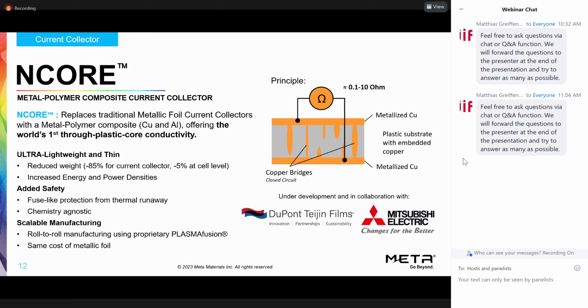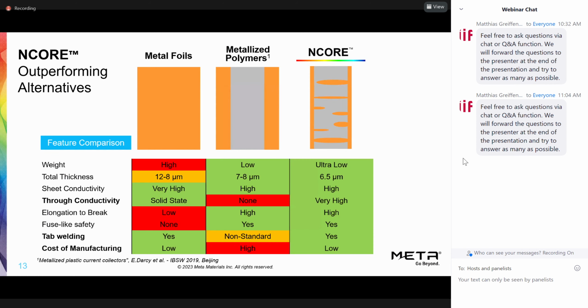Now, let's see how Encore outperforms the alternatives. Typical current collectors made of solid copper foil are heavy, accounting for more than 10% of the weight of the battery cell, and range from 8 to 12 microns thick. Metal-coated plastic substrates reduce the weight of copper, but do not provide through conductivity and pose difficulties with tab welding and high production cost. Encore is much lighter and reduces thickness to just 6.5 microns, which allows for more volume of active materials, increasing capacity and vehicle range.